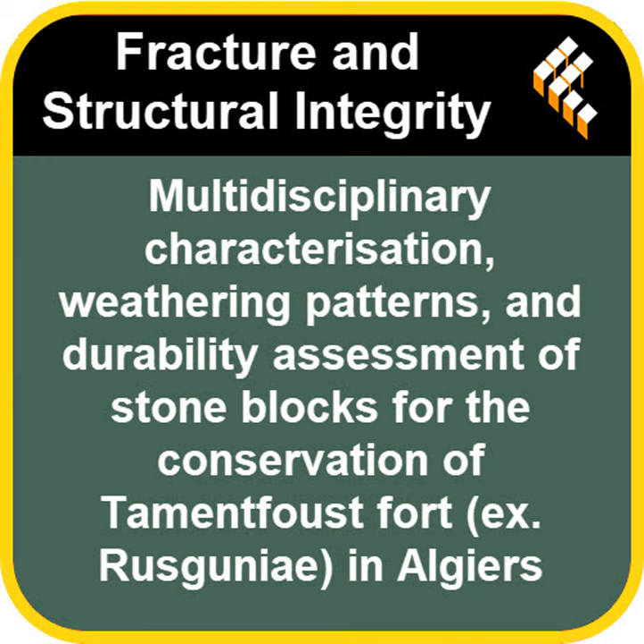But maybe the most severe was alveolization. Alveolization sounds nasty. It is. It covers about 20% of that south facade. It's basically severe cavity formation, like honeycombing, mostly caused by that salt crystallization and chemical dissolution of the calcite. So it all circles back, doesn't it? The location, the type of stone. Absolutely. The marine environment feeding it salt, the sun driving those wet-dry cycles, intensifying everything. It's just a relentless combination, a perfect storm of decay.